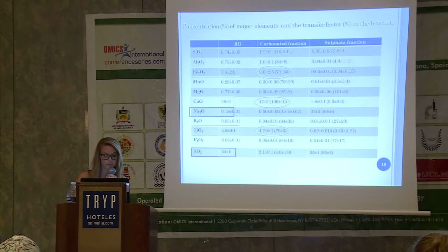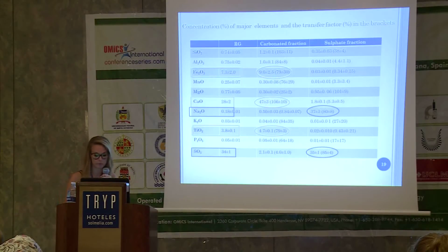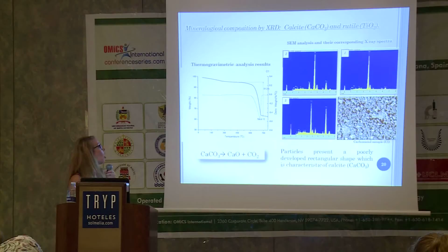But the sulfur and sodium are transferred to the sulfate fraction or solution fraction. Other techniques were used to characterize the carbonated fraction. And the main components are calcite and rutile. In this image, you can see that the particles present are poorly developed rectangular shapes, which is characteristic of calcite. The titanium and iron remain in these phases undisturbed.